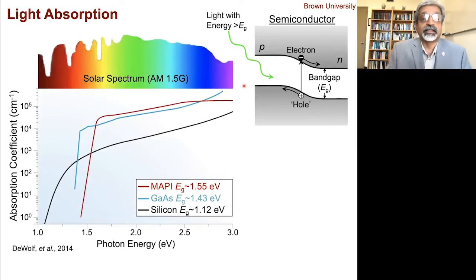That generates electricity, right? So light absorption is very important for photovoltaic material. So this is the solar spectrum, and this is light absorption of silicon. This is absorption coefficient, which is a log scale. So silicon actually is not a very good light absorber, but we use it because it's cheap and it's established technology.